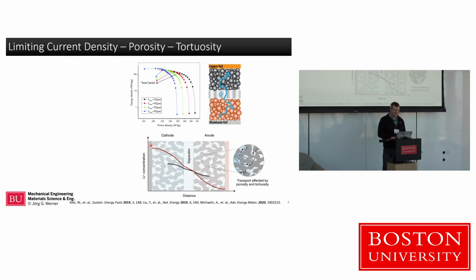If you make these layers thicker and thicker, you get to a gradient where you might reach a concentration of lithium ions of 0, somewhere close to your current collector. And at that point, you have to stop charging, otherwise your potentials go haywire and you start plating lithium and things like that. So your voltage really gets out of bounds once this happens, so we can't go beyond that point. We have to let the lithium ions re-equilibrate, or just be slower so they can replenish the lithium that has been depleted. Now there's been some work on this. Very simply, conceptually, of course, the more pores we have, the quicker the ions can move, and the more ions there actually are in the electrolyte, because you have more electrolyte volume, so you can get better charging rates or power. At the same time, the more pores you put into the system, the less energy you can store.